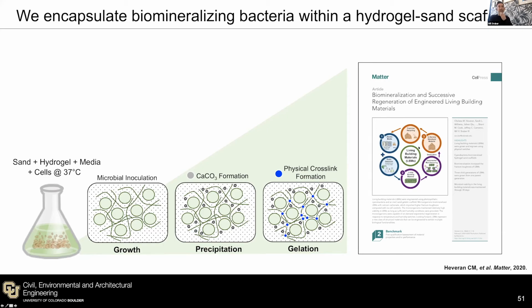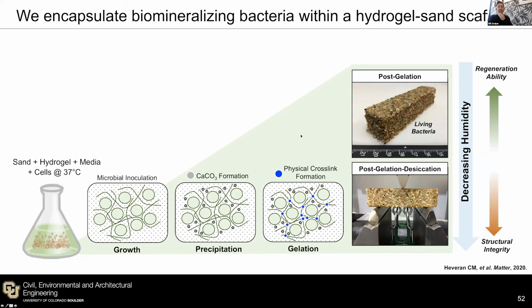And by the way, this is published in the journal Matter, if you want to read a little bit more technical details about it. But this is what it looked like. So this is post-gelation, right when we popped it out of the mold. And this material is just teeming with living bacteria that biomineralized inside, in between the sand particles. And then we were able to control the desiccation of that material and impart better structural properties with decreasing humidity. So there was this trade-off with keeping it gooey and squishy and keeping the bacteria alive versus drying it completely out and getting really good structural performance.